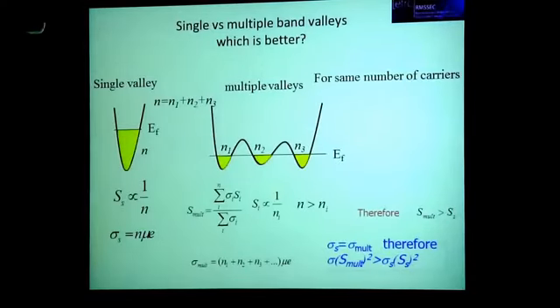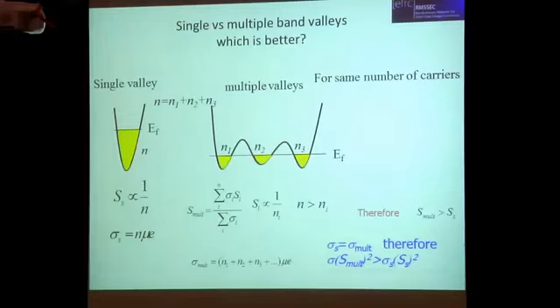So, for example, it's better to have the multiple pockets than to have a single pocket for a given number of electrons. Let's say if you had 100 electrons and you put them all in one pocket, your thermopower is not going to be as high as if you divided them 33, 33, 34 and had this situation. You can calculate mathematically that this would give you a higher power factor than that. So it's additive.